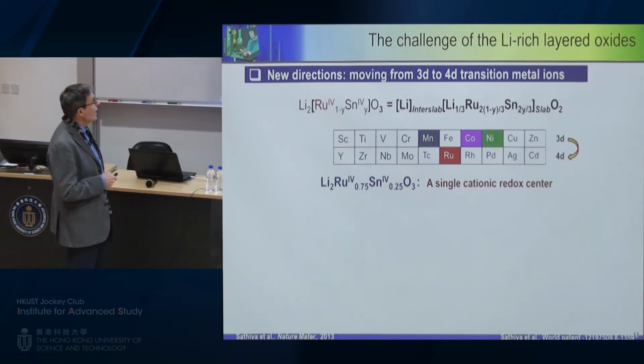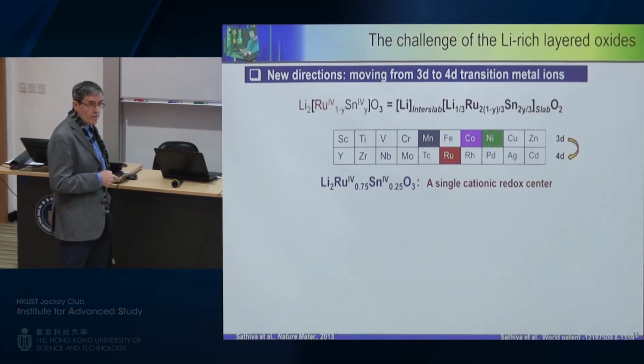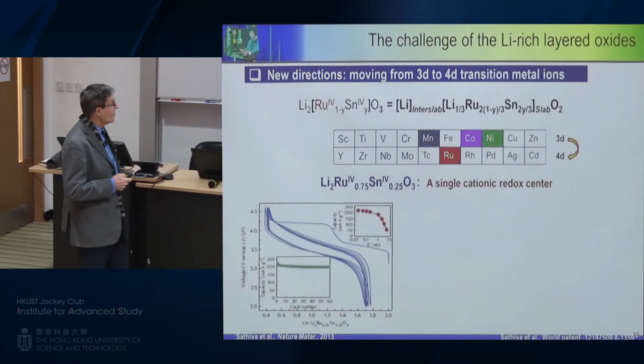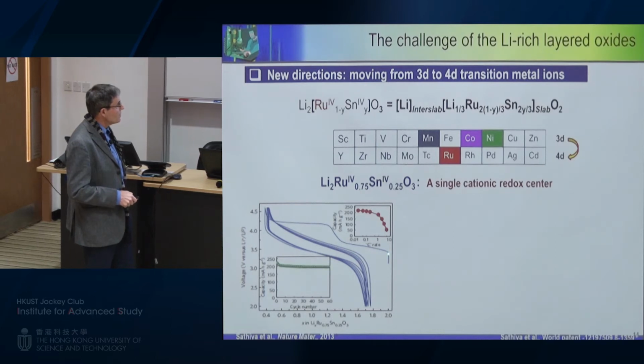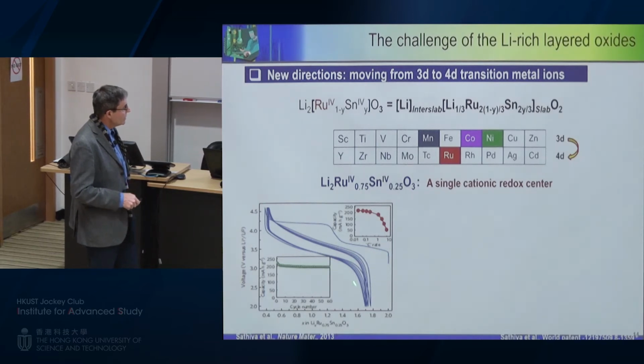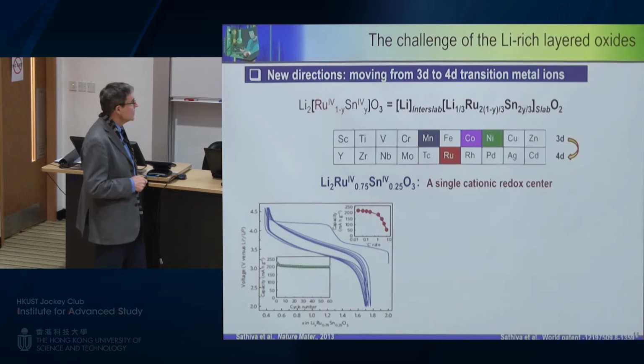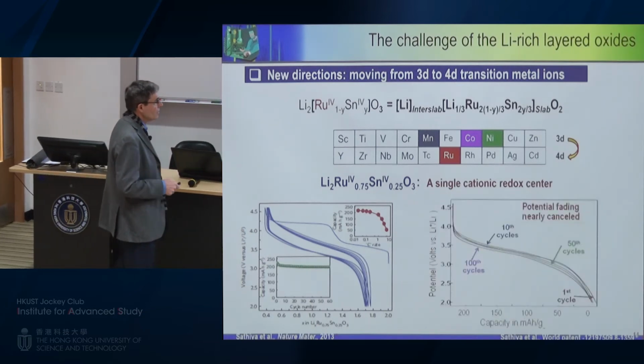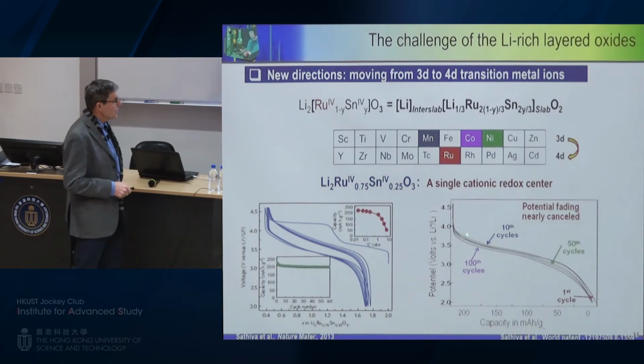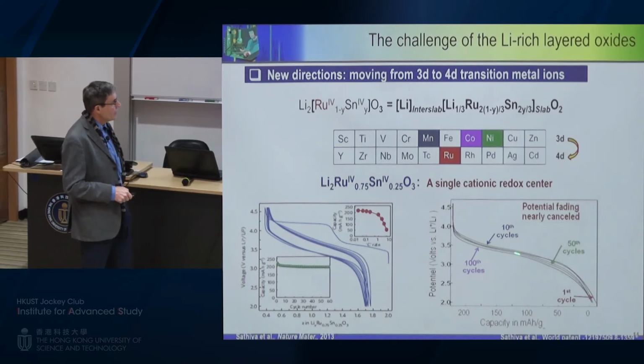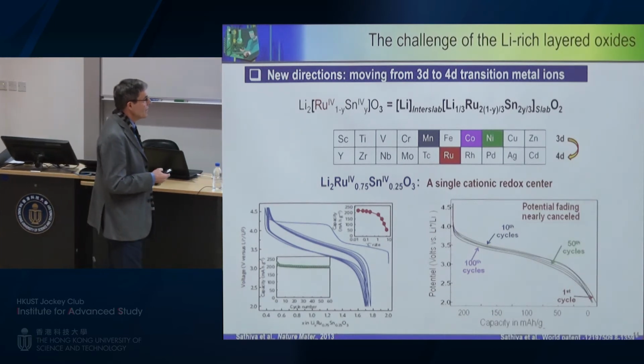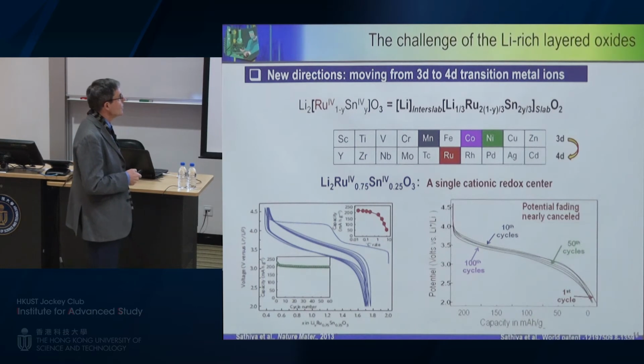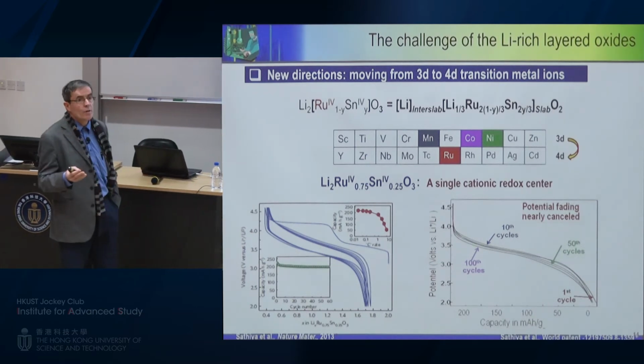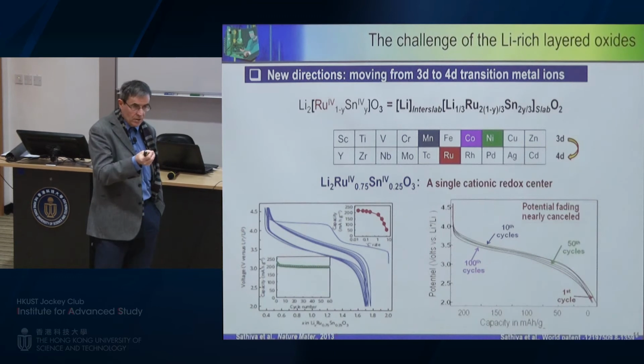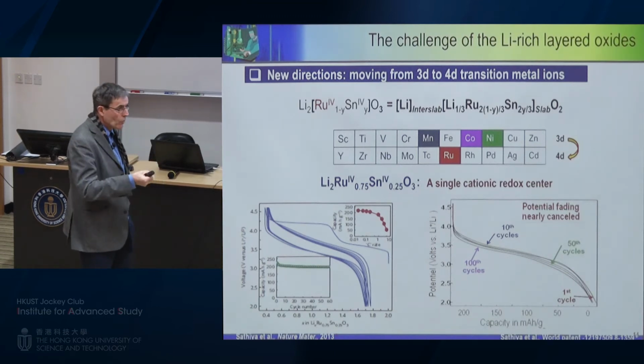And when you look at the properties of the materials, which by the way maintain the same layer structure, we found, as you can see here, the same type of cascade curve on charge, and then this S curve on discharge. When you look at the voltage fade, what was very pleasantly observed is that by doing this kind of chemical trick, we were able to not completely remove the voltage fade, but at least to partially solve it. So in this case, we finally designed a new material with a single cationic redox, which enables us to understand the basic phenomena.